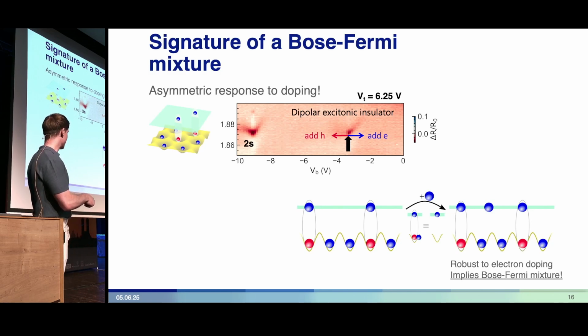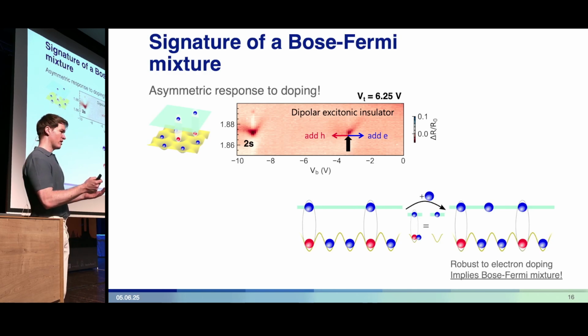We start from the dipolar excitonic insulator and add an electron, and this results in, whether we add it to the monolayer or to the Moiré layer, just a free electron living next to these dipolar excitons in the monolayer. It provides some screening, but doesn't fundamentally destabilize the Mott insulator which gives rise to the stability of the dipolar excitonic insulator. This alone already implies the existence of a Bose-Fermi mixture.